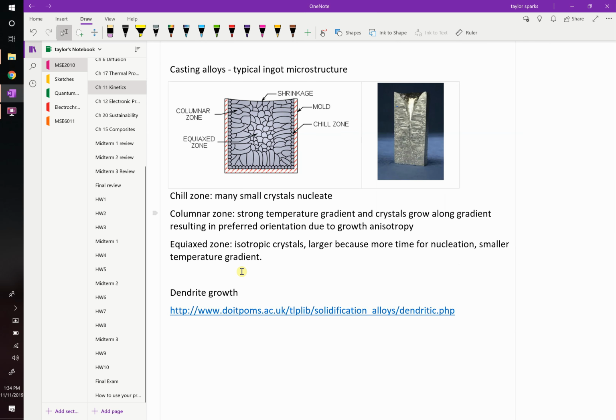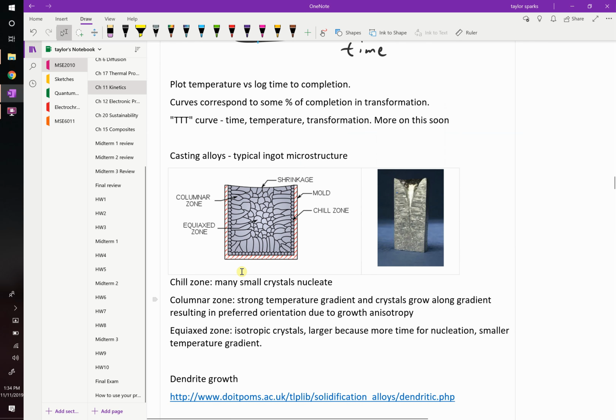So if you were to look at this thing, there is a temperature gradient across it. We could draw the temperature gradient as going like that, where that's higher temperature. It's cold out here, it's hot in the center, and so you've got this temperature gradient all through your crucible. What that leads to is columnar growth. You get this region right on the surface where it touches the cold crucible, if you poured it into there, and it forms little equiaxed grains.